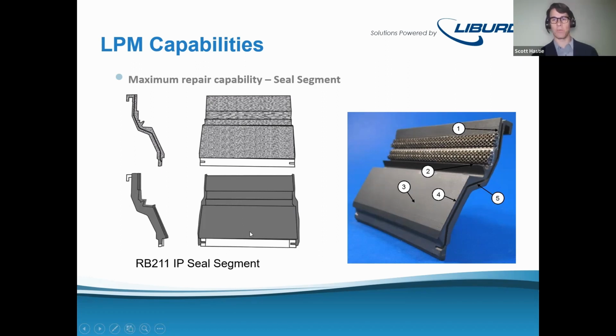And then we're taking what was once a cast surface and running a CBN grinding wheel along that surface that machines from here to here, all in one operation, and machines all of the geometry that will then become the gas path and honeycomb location features. We've got a little bit of extra EDM work to do to make a seal, but I think the key thing for this repair is re-EDMing out these seal slots.